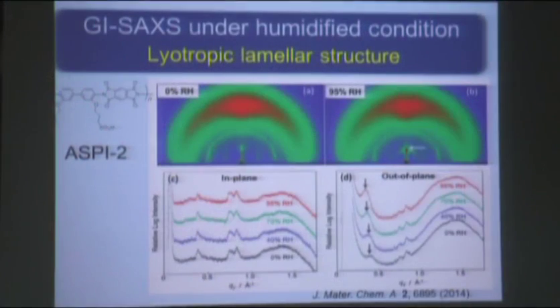Increase the humidity, red one, but the in-plane diffraction does not change. But out of plane cases, this is different. From the dry to the red one, you see that this peak is moving to the lower value. So this means totally anisotropic structures. By analyzing this, we can see the lyotropic lamellar structure based upon the liquid crystal properties.